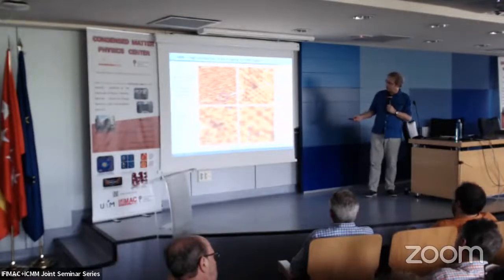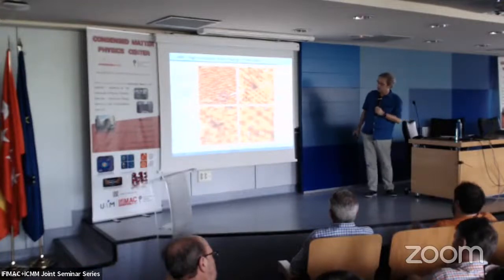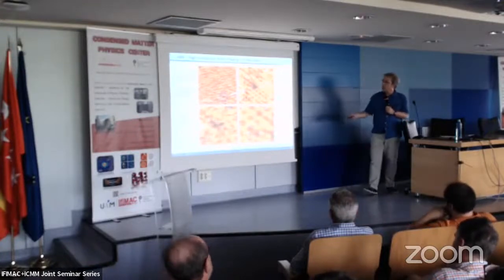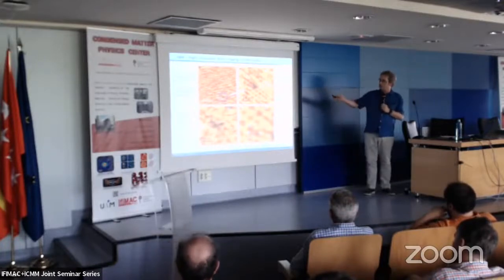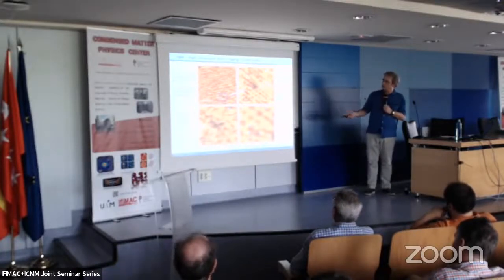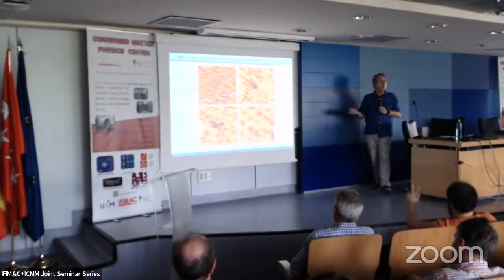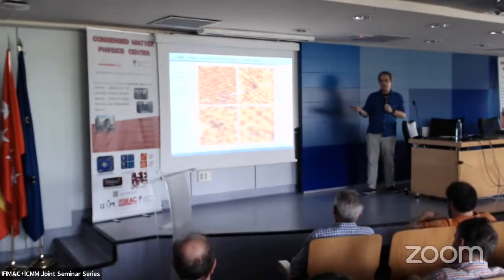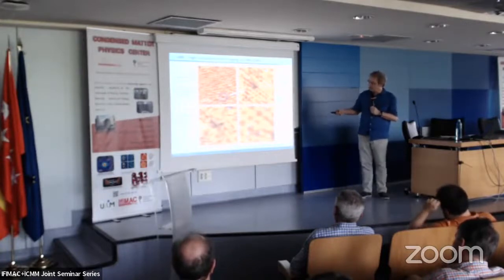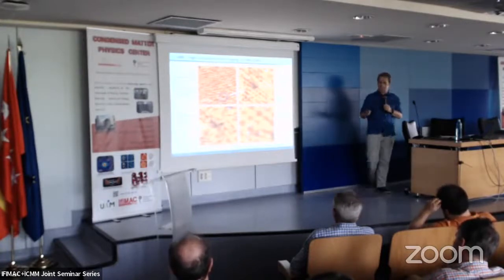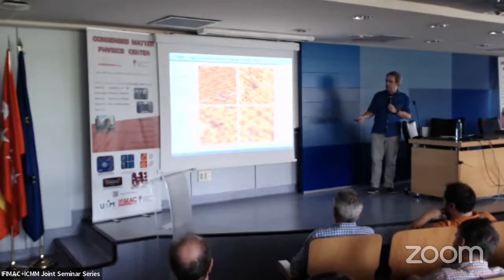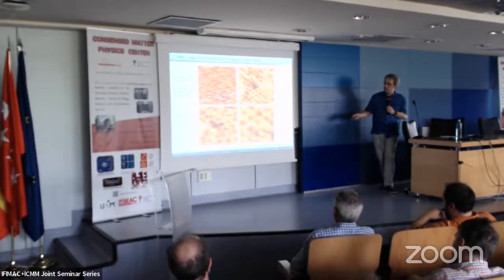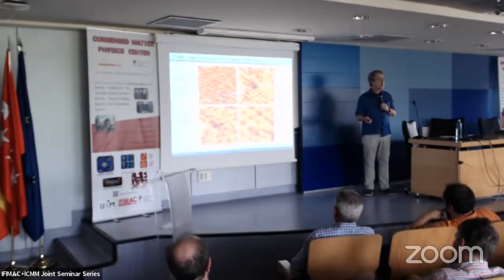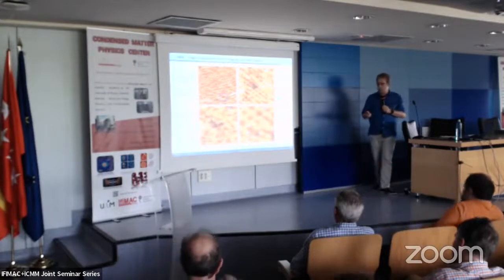Here the nitrogen is in the boron site and the nitrogen is missing, so the vacancy of the nitrogen. In this image, these drawings of boron nitride are tentative because these pictures have a very good resolution, but you cannot really detect which one is boron and which one is nitrogen. But this corresponds quite well with these kinds of defects. This defect was mentioned already by one of the first publications as the origin of this emission.